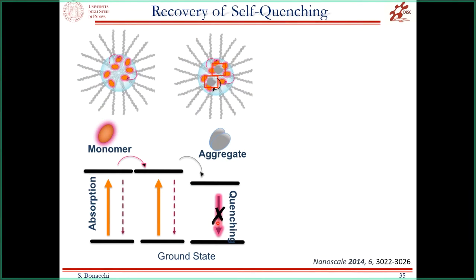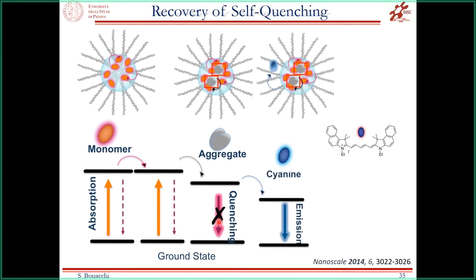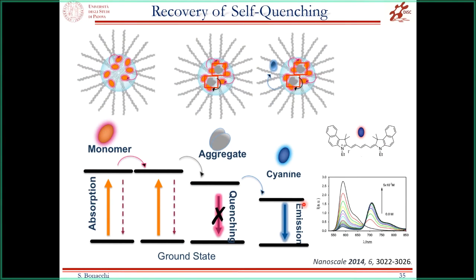And the solution that we found, I would say the smart solution, is to use a red-emitting energy transfer acceptor, like a Cy5. This is not hydrophilic. So as soon as we add this cyanine inside our water solution with nanoparticles, it tends to go inside the PEG of the silica nanoparticle and stay there trapped, for hydrophobic reasons. And as soon as we trap the cyanine inside the PEG, this activates another energy transfer phenomenon between the monomer, the aggregate, and the lower-emitting cyanine layer, which acts like a final acceptor of this energy transfer and could help us recover the quenching of the brightness that we observed before.